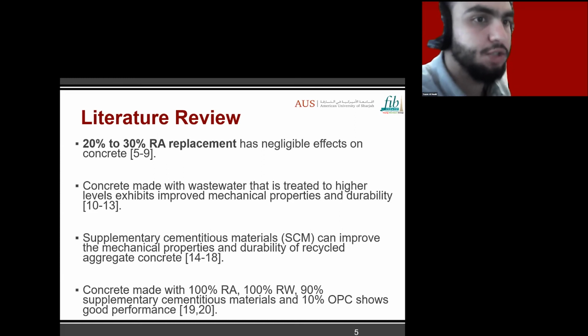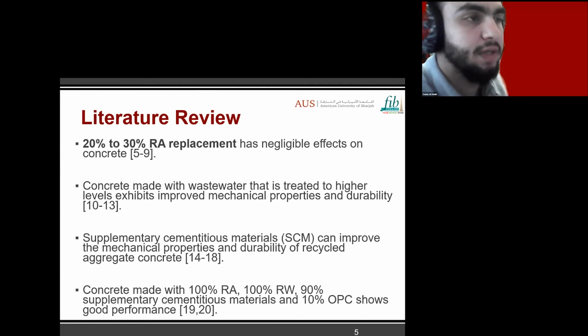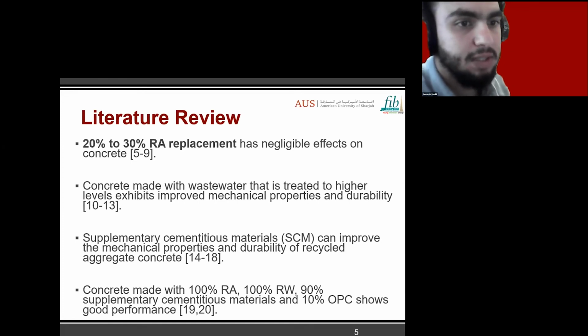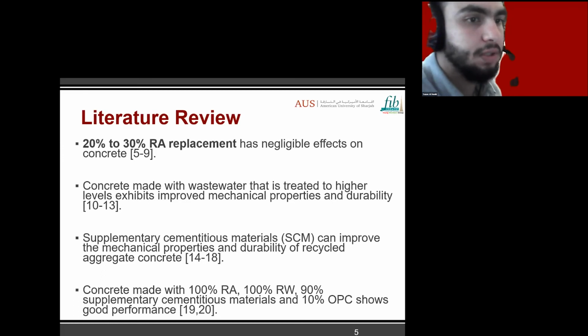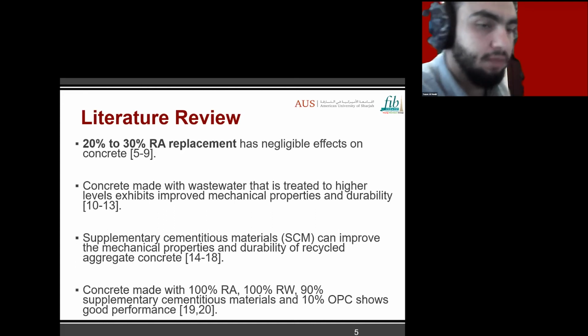Previous research has shown that the properties of concrete made with recycled aggregate can be improved with the use of supplementary cementitious material. Few studies show that using 90% supplementary cementitious material and 10% OPC can produce concrete made of 100% recycled aggregate and 100% recycled water with good performance, without losing any of the strength of the concrete.